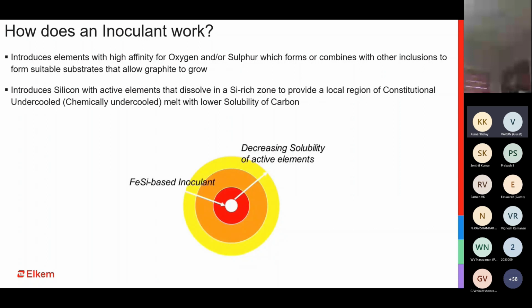So basically inoculant is a ferrosilicon alloy with some additives into it. The additives are the inoculating elements, which I had mentioned a few slides back, can be barium, calcium, strontium, zirconium, manganese, rare earths, bismuth, etc. What do these elements do? So these elements are chosen. I mean, the question can be, why only these elements and why not the rest of the elements which we have on the periodic table? So these elements have a very strong affinity towards oxygen and sulfur. So when they have a strong affinity towards oxygen and sulfur, they combine with the oxygen present in the system. They combine with the sulfur present in the system, and after combination with the oxygen and the sulfur, they create those inclusions, those small substrates on which the graphite would eventually precipitate.